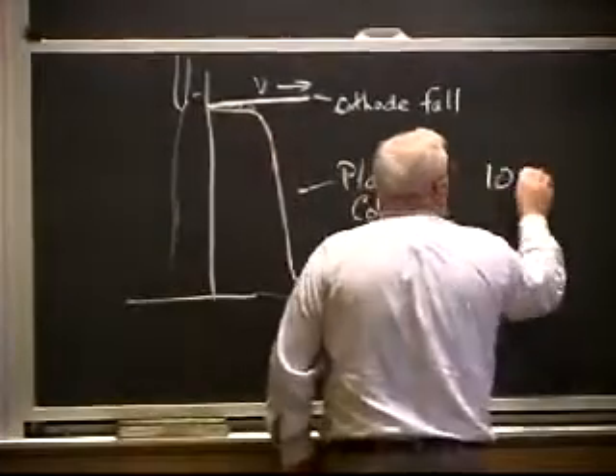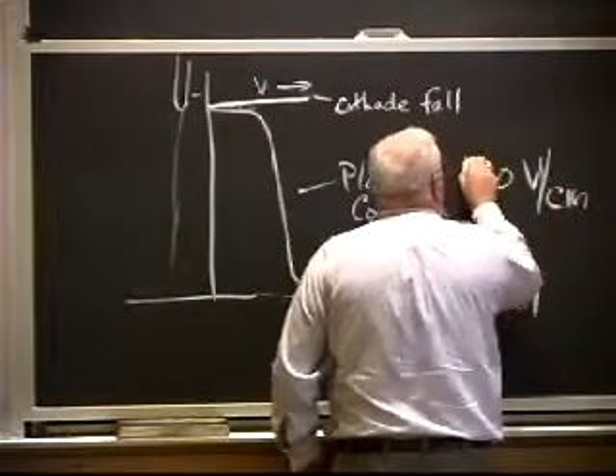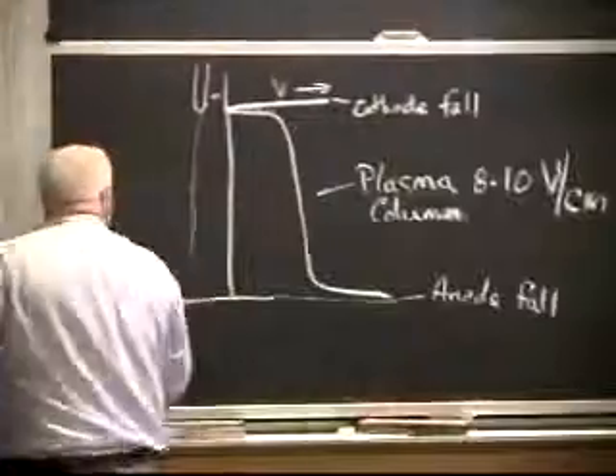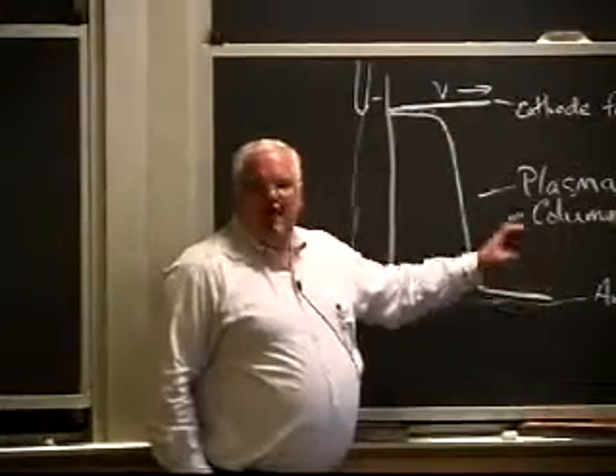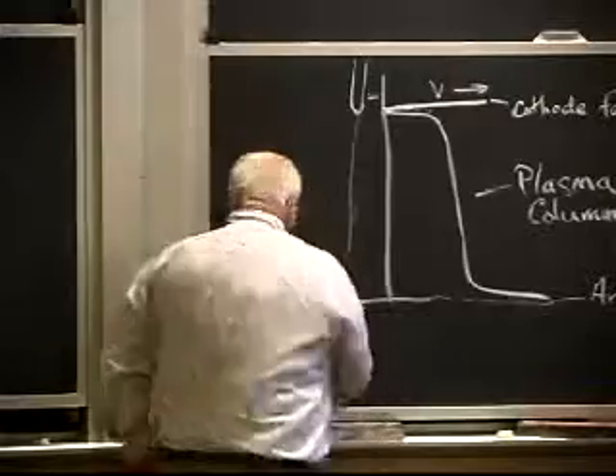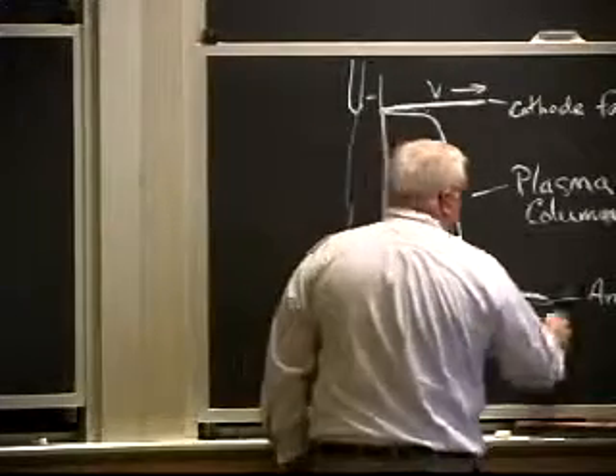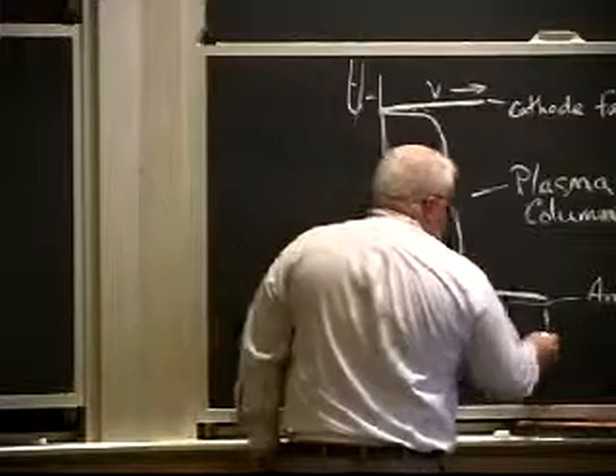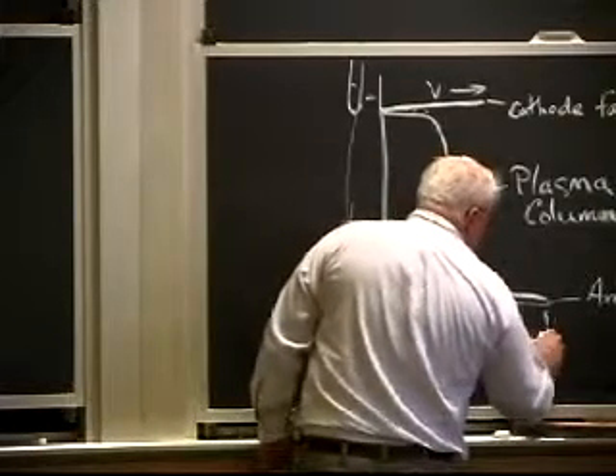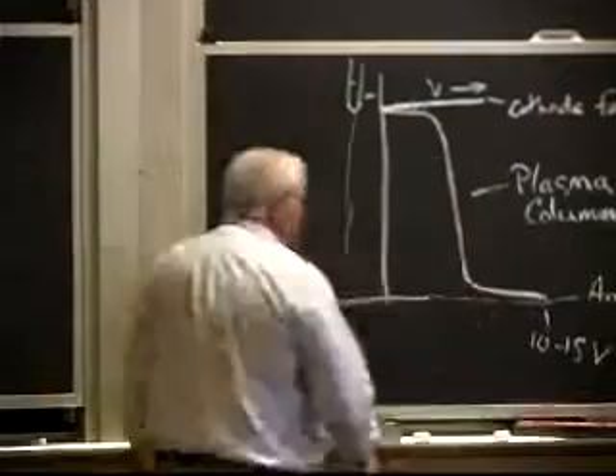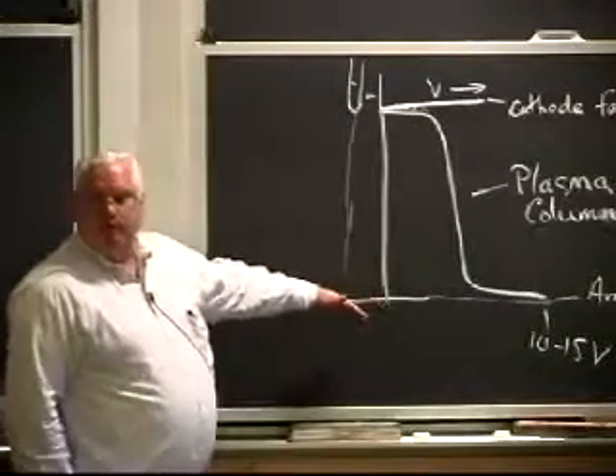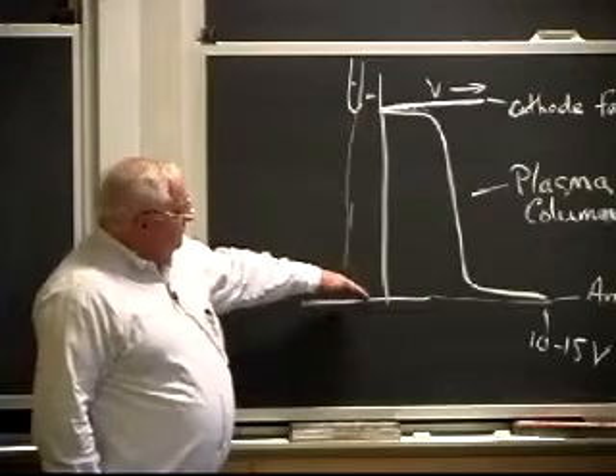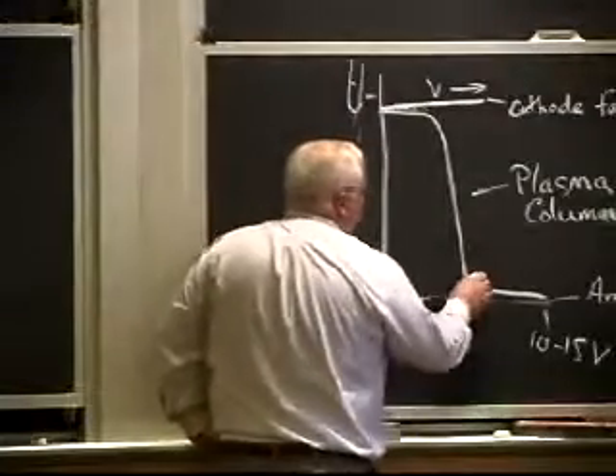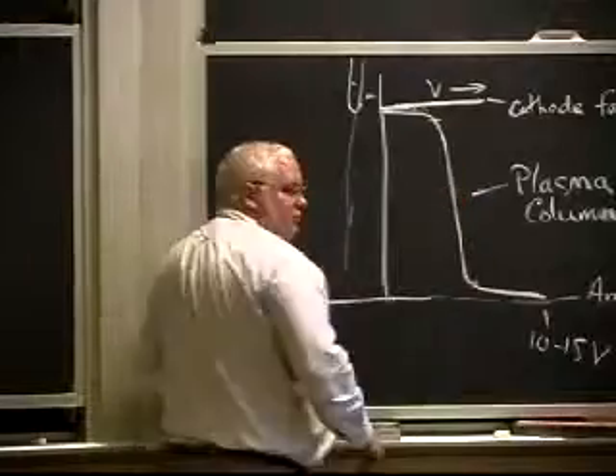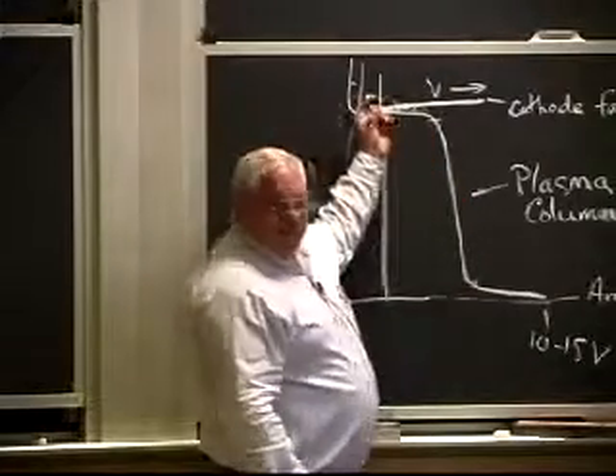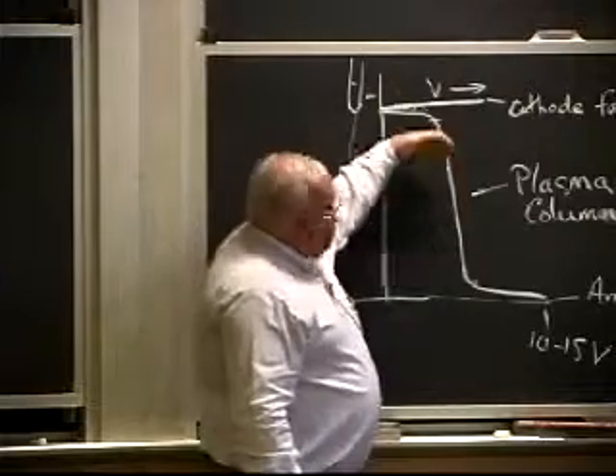In the plasma column, you have an electric field strength of about 8 to 10 volts per centimeter. But in the cathode fall and the anode fall regions, you have much higher voltages. If this is an atmospheric pressure arc, 1 atmosphere overall pressure, with a tungsten electrode up here, the total voltage might be 10 to 15 volts for a tungsten electrode. This distance might be half a centimeter or a centimeter. That's a pretty long welding arc for gas tungsten arc, but this would be a gas tungsten arc with a tungsten electrode, and you would have argon as a shielding gas.